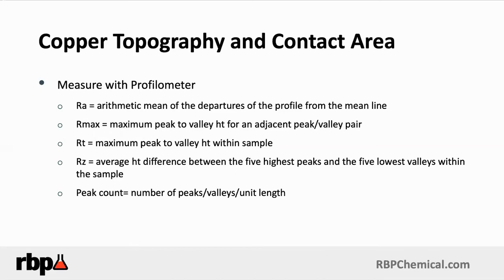And of course, the copper surface also has to be free and clear of other issues as well, such as residues and chromates, and we'll talk about that. But know that understanding the mean roughness of a surface and how to get there is really key, whether it's mechanical preparation, pumice preparation, or chemical preparation, but more on that later. I also wanted to note that if you have a surface that's very rough and very non-uniform, that's not going to help you with photoresist adhesion either. That's going to cause other problems such as undercut, potential etch outs, and opens in the circuit. And we'll talk about that very shortly.